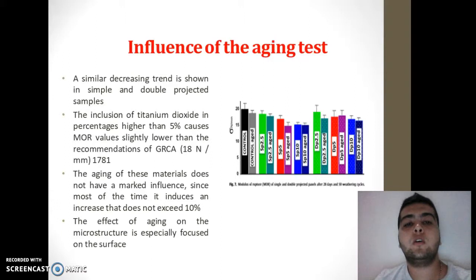And the inclusion of titanium dioxide in percentages higher than 5% gives values distinctly lower than the recommendation made by the standard. And the aging of this material does not have a marked influence, since most of the time it induces an increase that does not exceed 10%.